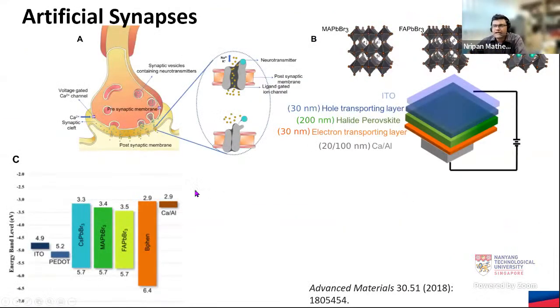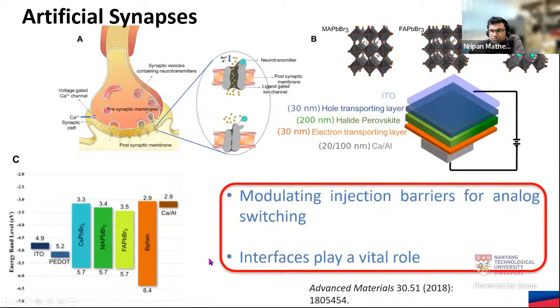So what we did was to add on other interfacial layers. We still use the same halide perovskites, the 3 perovskite layers mentioned in the previous slide. And we have electron transporting layers and hole transporting layers added onto it. So these are the different layers that we added onto it. The logic we wanted to follow was, we know that the halides can move within these perovskites. We know that p-type and n-type doping can happen. We also suspected that halogens would be able to move into the interfacial layer and dope it. So could we utilize the interfaces to do analog type switching?